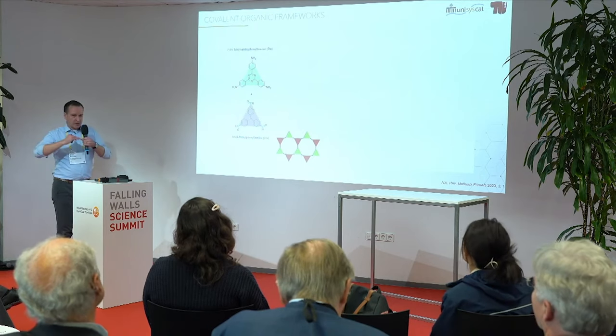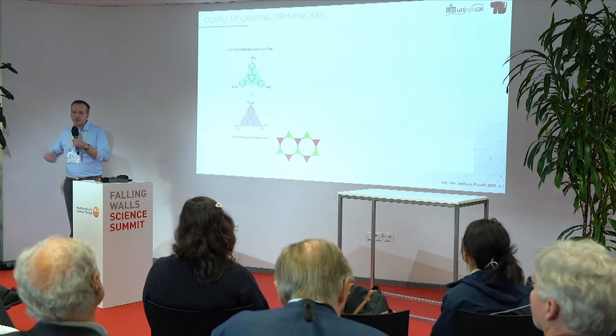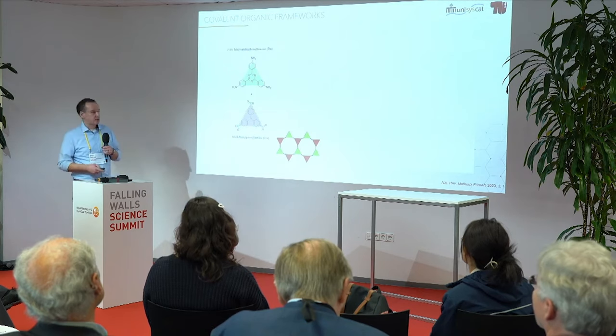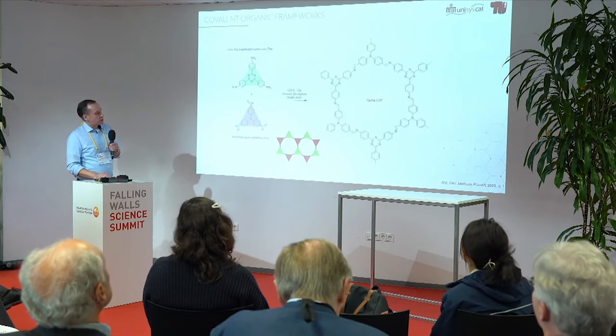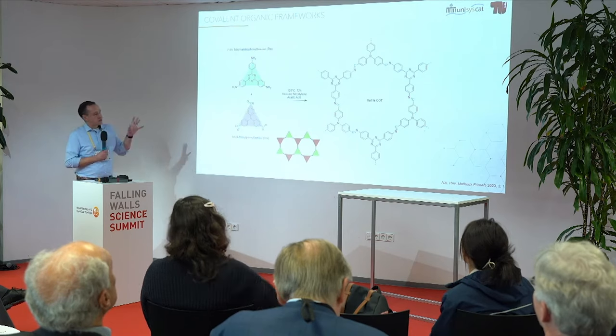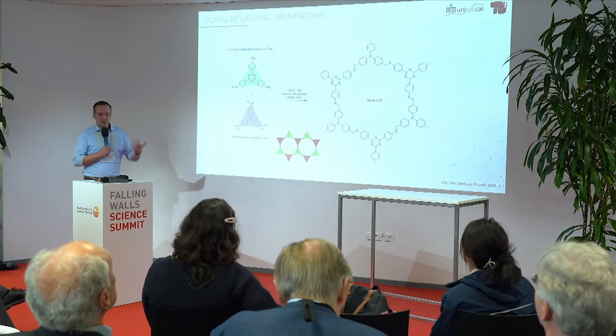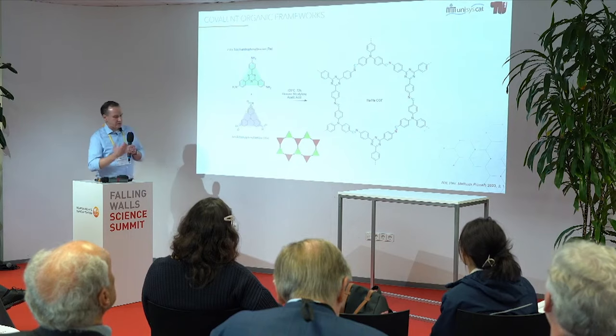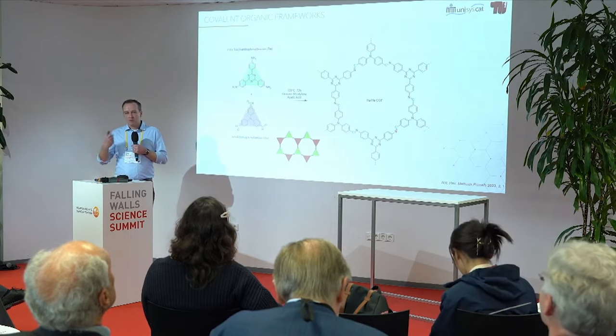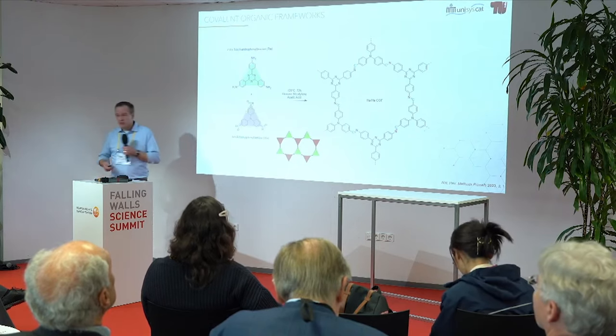If I put triangles together in a planar way, then I should have a 2D layer which forms a honeycomb structure, or a 2D hexagonal structure, as we call it. And that would be the material we are producing here, so we have to find the right conditions to do this. It's a reversible synthesis, so that the thermodynamically stable material is formed, and this is crystalline.